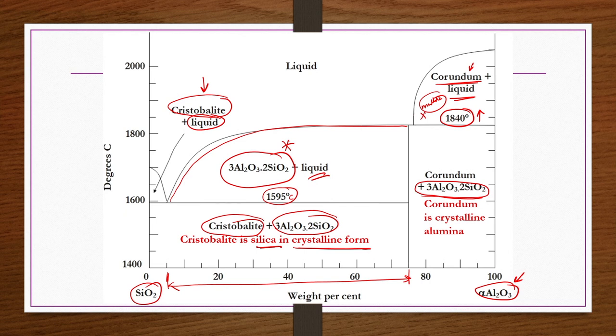But if you go beyond this temperature, you don't get mullite here. Right, here also for the silica, which is almost pure silica with little alumina, if you go beyond the temperature of 1595 degrees centigrade, you get liquid as well as cristobalite silica, but you don't get any mullite. Mullite has been found to be a very good refractory.